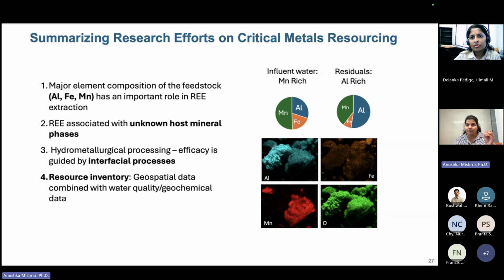So we are able to use ICP-MS to measure them. However, for SEM, let's say REs are low, but cobalt is a little higher than the RE concentration. When we do those analyses, the iron that we are detecting can easily interfere with cobalt. You cannot detect how much cobalt is present just because you see a large peak coming from iron. And these kinds of challenges will also exist when you look at different characterization techniques, like peak overlapping. And I think for the MS, it's right now very clean.